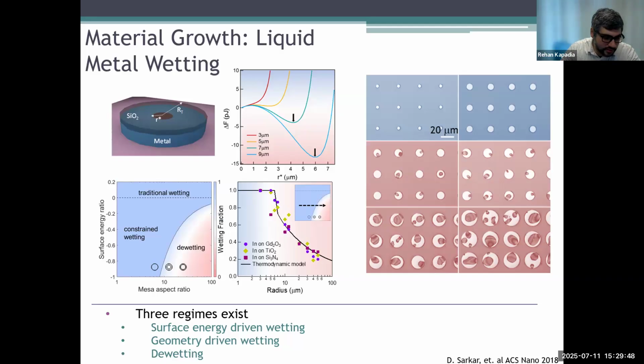And if you don't follow that constraint, what ends up happening is that you can end up getting de-wetting. But the moral of the story here is that we have a good thermodynamics-based, surface energy-based model. For example, over here, the black line is our model for how we expect things to happen. And then all of these dots are de-wetting tests on different substrates. So the moral of the story there is that we think we understand it. And again, we have a basic material model that is not calibrated, but that matches with experimentation. And so we have a reasonable understanding of the material science of what's happening there. And the takeaway is that depending on what you want to do, there are some geometric constraints, but as long as you can follow those geometric constraints, you'll be able to use this approach to grow on any substrate that's inert to what you're growing.